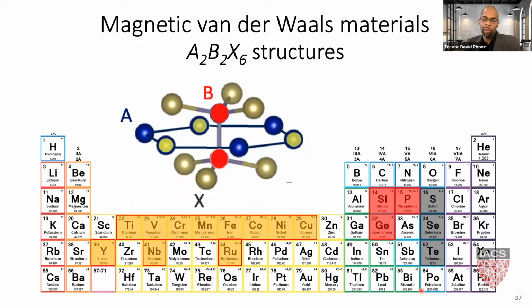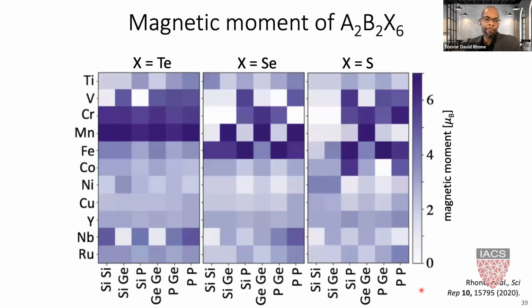So let's look at the magnetic moment for different A2B2X6 structures. That's shown here, where the vertical axis is the A site substitution, the horizontal axis is the B site substitutions, and the panels are the different X sites. For instance, this material here represents chromium 2, germanium 2, tellurium 6, chromium germanium telluride, and it has some magnetic moment somewhere around here. If you made a substitution of the A site to manganese, you get an even larger magnetic moment, a darker purple color. And if you make some substitutions, the color becomes lighter, meaning that the magnetic moment is greatly reduced.